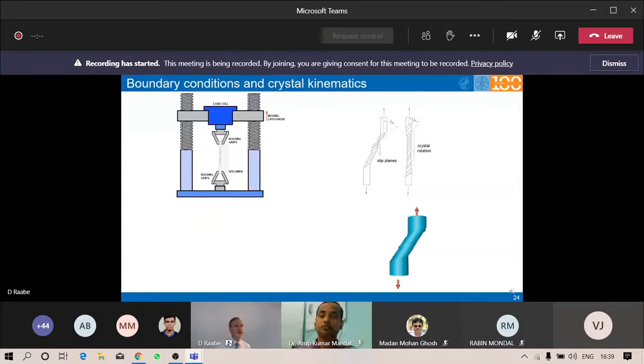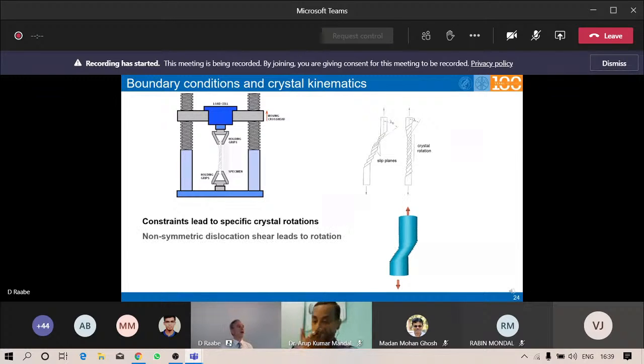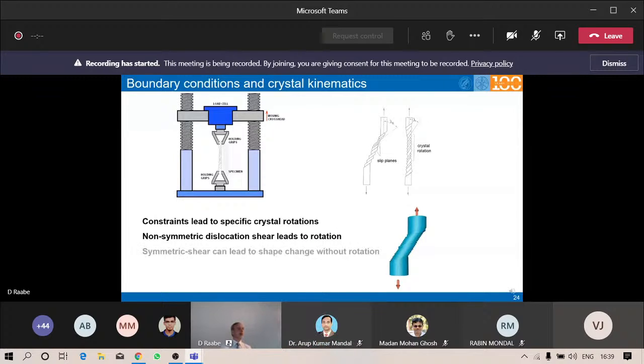And that means you have these geometrical constraints, these boundary conditions that enforce certain crystal rotations. And the fact that these boundary conditions are not homogeneously distributed across the expansion of such a crystal means that you can also have gradients of such crystal rotations from one surface to the other, which very easily explains why often the texture in micromechanical evolution is very heterogeneous even inside grains. So I found this view graph maybe helpful because even such a simple kinematic point can be made readily clear on such an example.